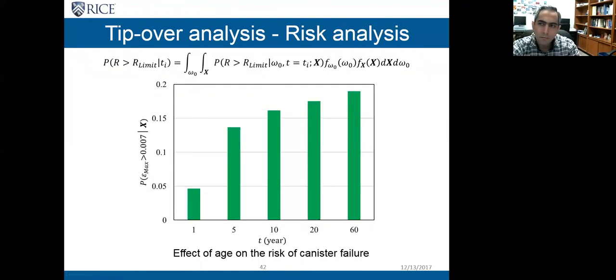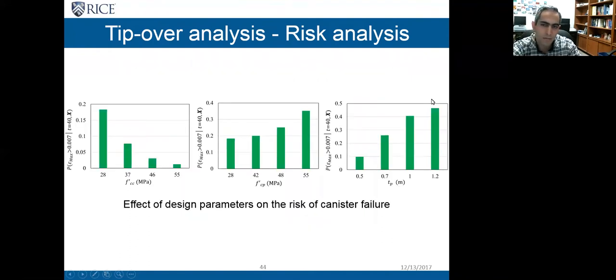Another application of the meta model and the fragility analysis is the risk estimation. So we can integrate over the fragility and estimate the risk. This figure shows how the risk in the tip over problem varies with time. And as we see, for older casks, we have more risk of failure. And the same pattern that we observed in the sensitivity analysis applies here. I mean, a stronger concrete in the overpack reduces the risk, but a larger strength for the concrete in the pad, and also a thicker pad, increase the risk.